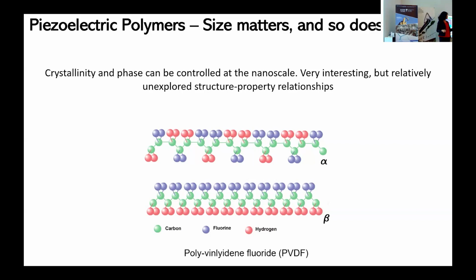Now, there is a dipole present in this structure. You have a dipole going from the more electronegative fluorine to hydrogen, so it's perpendicular to the chain. But in this random configuration, you can see that the dipoles basically cancel out. So this phase is not piezoelectric. In order to induce piezoelectricity, I need a sustained dipole, right? I need a polarization in the chain. And for that, I need this beta phase, where you have all the hydrogen and fluorine atoms lined up nicely across the chain. So this is the all-trans configuration. Here, I do have a net polarization in this structure.